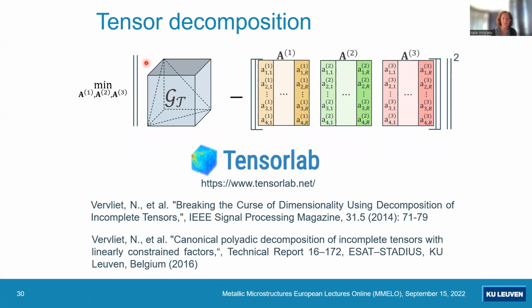They can be obtained using a minimization procedure. So typically you compute a lot of Gibbs energy data, you call it the training data, and then all these elements in these factor vectors will be determined in such a way that the difference between the computed Gibbs energies and the approximated is as small as possible.